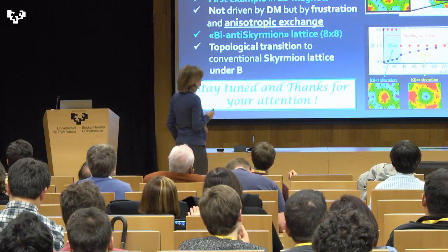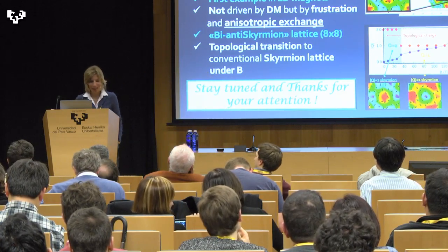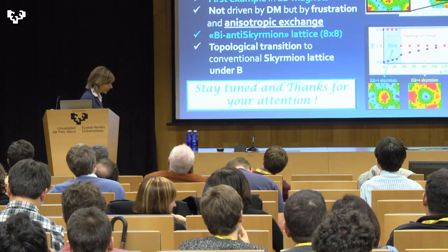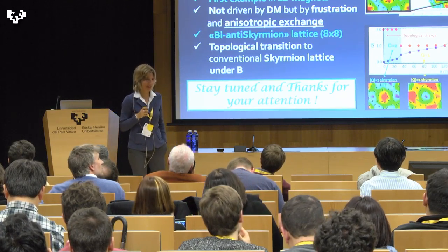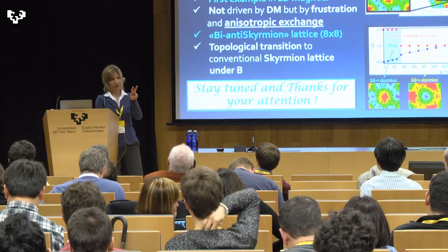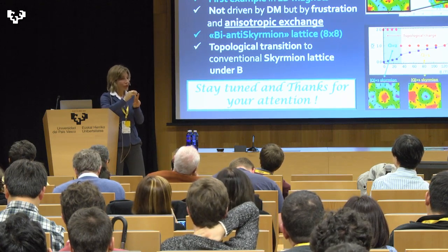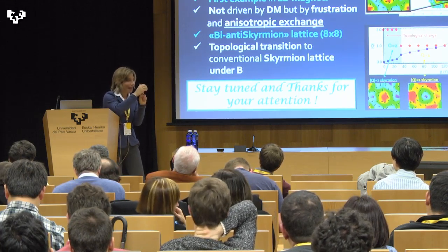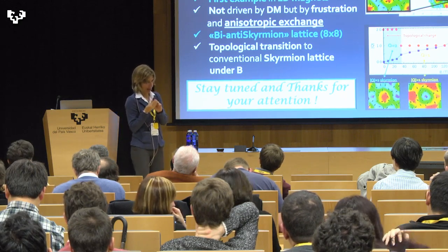That's a good question because it's related to both. In DM it's typically D over J. Here we have 2 ingredients because there are 2 scales. So J3 over J1 is probably something, and then JZY over J1 is the other scale.